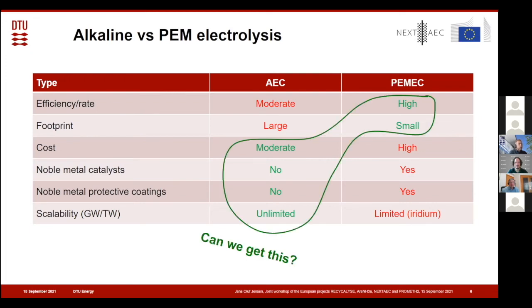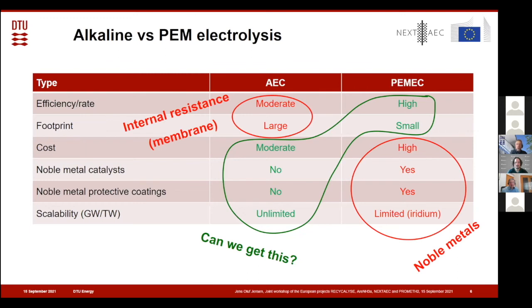So it is tempting to look at just the green words here and say, can we get this in one system? And we believe we can do that. Then we have to look at what gives the red writing. For the high cost, it is the noble and expensive metals, especially the iridium, that limits the scalability. And in the alkaline system, the big problem is the internal resistance. That's why the polarization curve, the voltage-current profile, rises so sharply, because as soon as you increase the current, you have an ohmic loss, that's Ohm's law, basically, in the membrane. That is not so pronounced at low current densities, but at high current densities, this is the main source of losses and heat evolution. So if we get a better membrane in that case, it would be very advantageous.